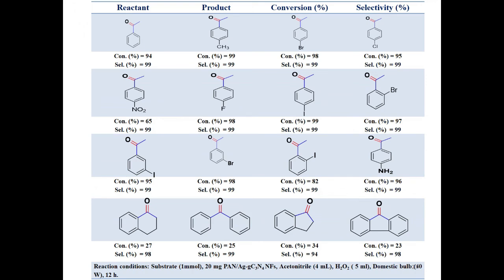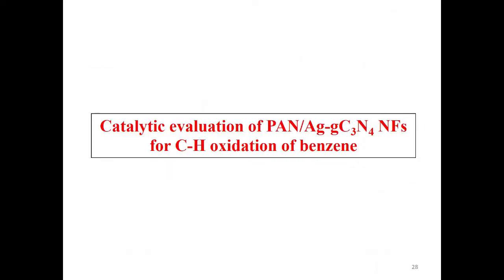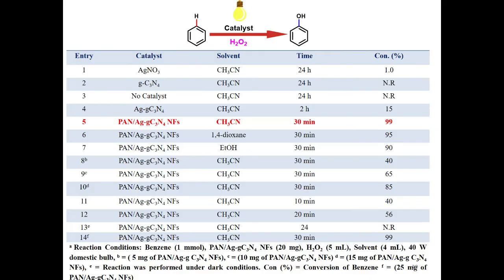So these are the different reactants, their product, conversion, and their selectivity. So you found that this nanofiber, that is the PAN/Ag-gC3N4, is very selective, and conversion rate is very high for that particular reactant. That is CH oxidation of benzene, means whatever CH bond is there undergoes oxidation, and there is a formation of phenol. With the same solvent condition, the reaction time is 30 minutes, and it gives 99% yield as compared to the other catalyst or other solvent condition. Time required is very less also.